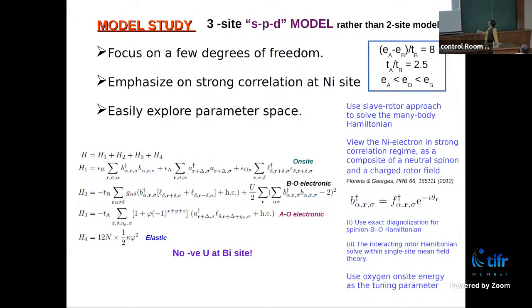I only see Vikram. But anyway, that is basically where you break down this in terms of some spinon, which is a neutral thing, and a rotor field, which is a charged one. What you achieve by this separation of variables is an exact diagonalization, which is basically a non-interacting problem of the spinon, bismuth, and oxygen Hamiltonian. There is no correlation effect. All the correlation effect gets into the rotor field, and that was solved with the single-site mean field theory. And we use the oxygen on-site energy as the tuning parameter because by putting pressure, that's all you are doing.